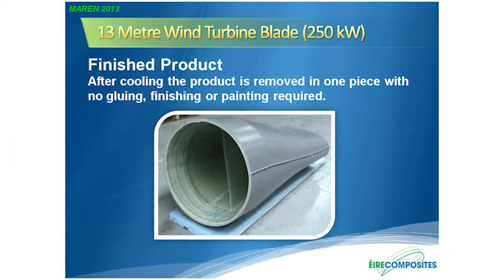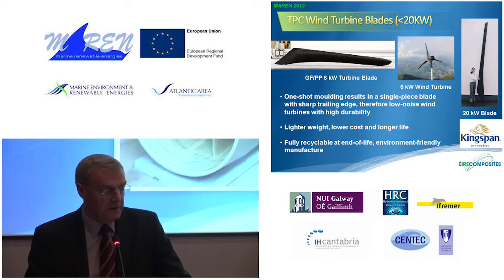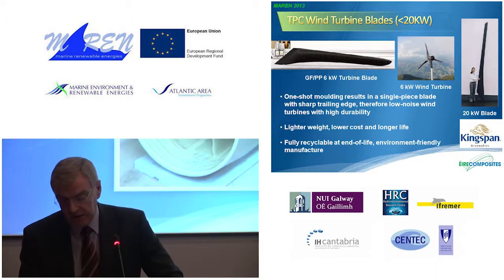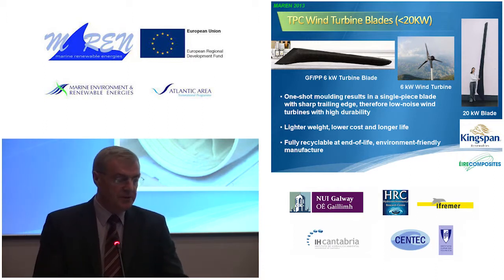And what you get is this, a part which has a surface finish on it. It's been molded all as one piece. That's the way it comes out of the mold. So you have no gluing, finishing or painting. The only post-molding work is to remove any flash that might be on the edge of where the molds join.